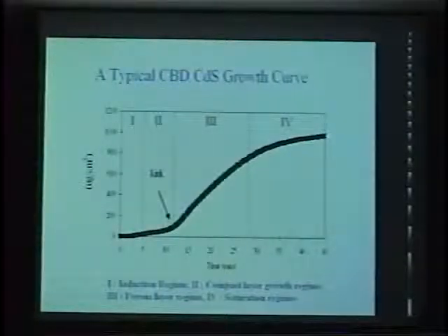As a function of time, you can see actually there's about 4 regions. Okay, so first is the induction region. Mostly probably related to the adsorption. It takes some time for the reactant to go to the surface. So at this time you don't see much growth. Then you have a linear growth region, which is more of the molecular level growth. Then suddenly you have a much faster growth, and that's related to you form a lot of particles, right?